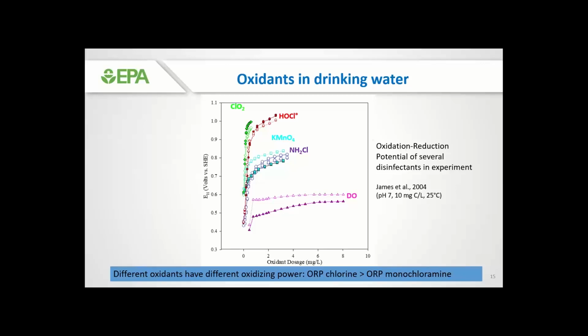So at the bottom of the graph, you see data for just dissolved oxygen, no disinfectant added to the water. In the middle, you can see monochloramine, NH2Cl, and at the top with the red color and the green color, you can see chlorine species. So different oxidants really truly have different oxidizing power. For example, you can see here that ORP for chlorine is higher than monochloramine.